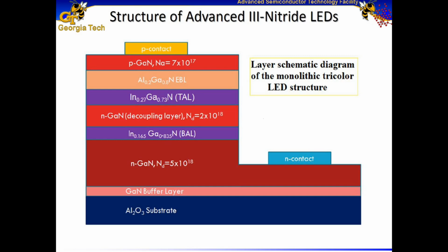And similarly, we can achieve up to a maximum of 40% indium content in terms of the growth. I mean, there are some groups, for example, the group of Dr. William Allen Doolittle from Georgia Institute of Technology, they are able to achieve indium gallium nitride in the entire alloy range, but a lot of people are only able to achieve up to 40% indium.